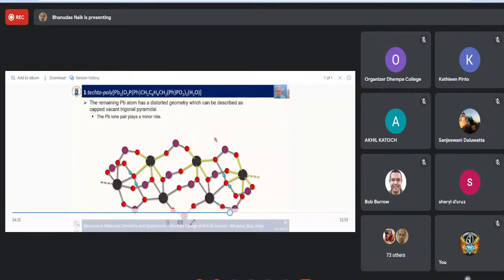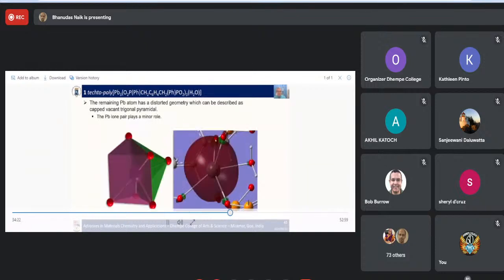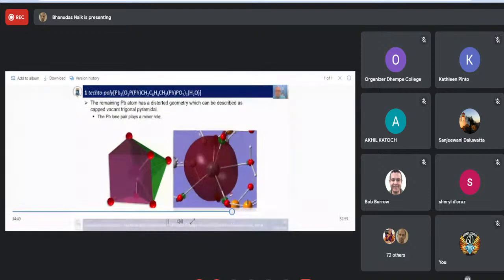This compound here, in this case, is a hemidirected center. You can see in this case, if you map it out, the lone pair would be about this position here, and you can calculate that out, and it's about the same position here. You can see the large HOMO. This is the HOMO orbital of the lead, and you can see that it bulges out a bit more in this direction here.